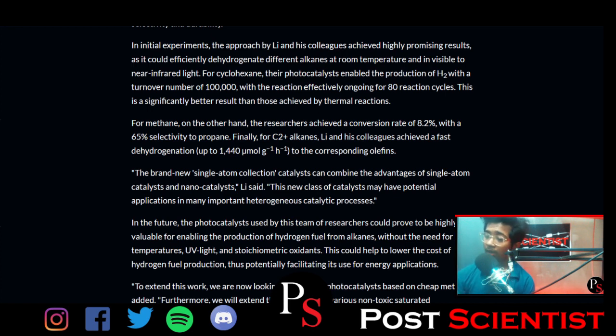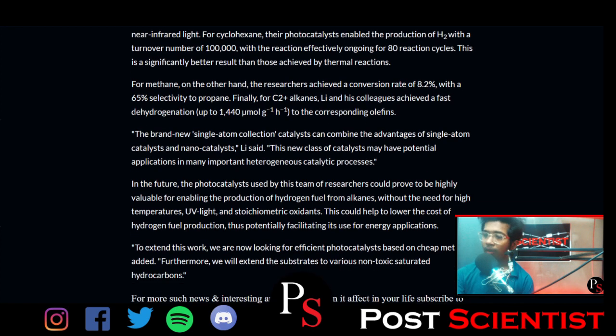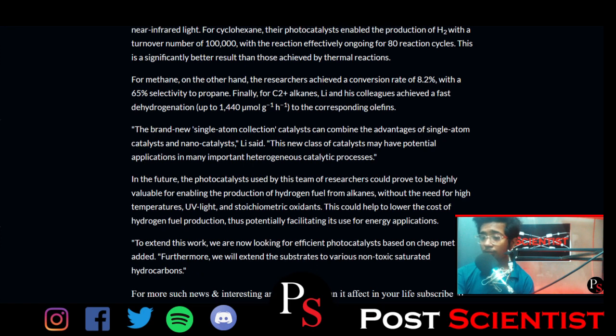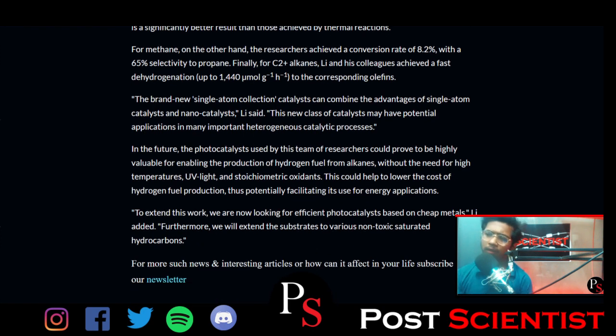For cyclohexane, their photocatalyst enabled the production of H2 with a turnover number of 100,000, with the reaction effectively ongoing for 80 reaction cycles. This is a significantly better result than they achieved by thermal reaction. For methane, on the other hand, the researchers achieved a conversion rate of 8.2% with a 65% selectivity to propane.